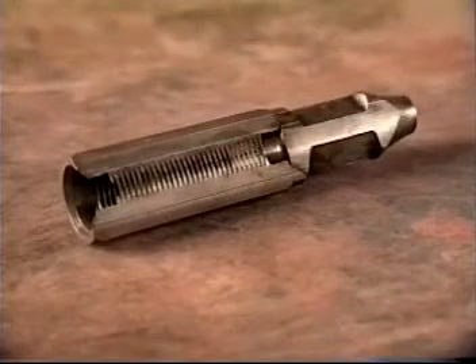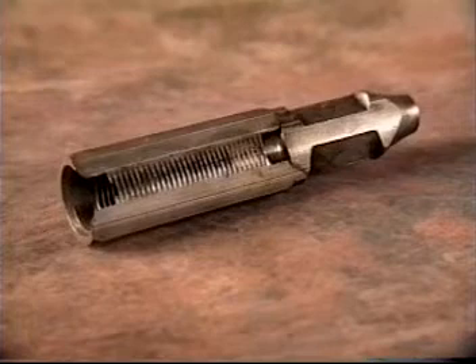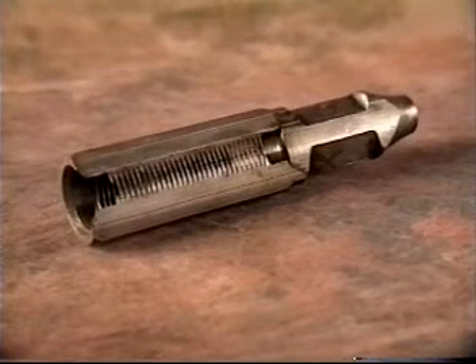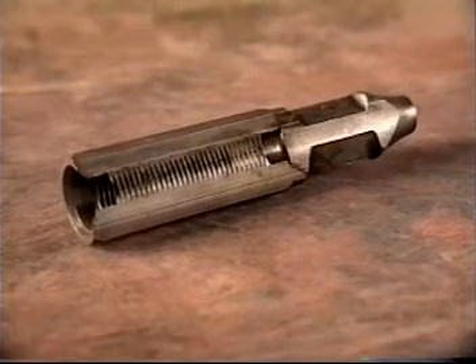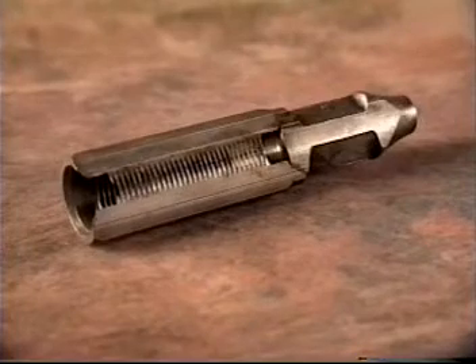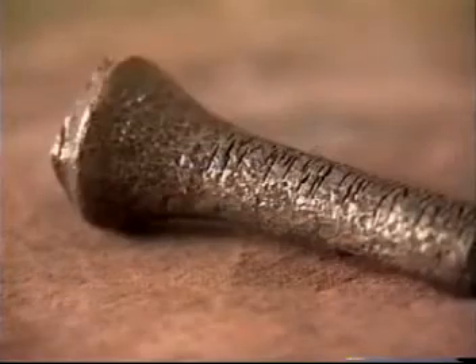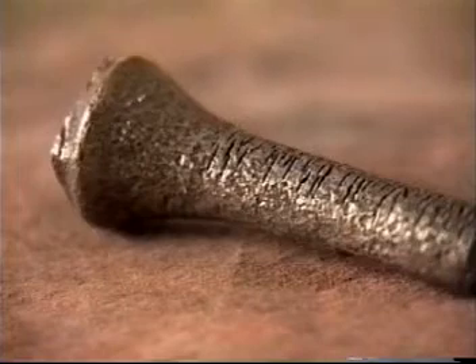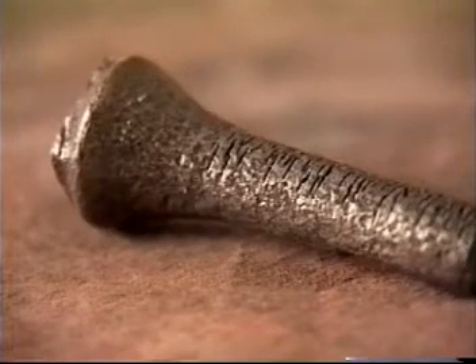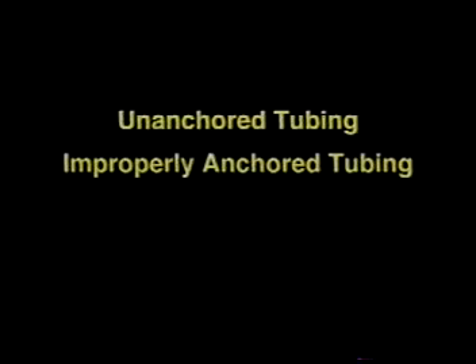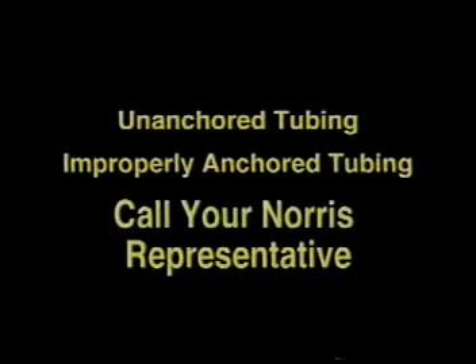Compressive loads will usually result in distinctive wear patterns on the couplings as well as the sucker rods. Look for longitudinal wear patterns that completely erode the walls of the couplings and the rods. Compressive loads also cause transverse stress cracking due to flexing when the rod buckles on the downstroke. Unanchored or improperly anchored tubing can also induce severe wear on steel sucker rods and couplings. Diagnosing rod or coupling breaks that may be attributable to unanchored or improperly anchored tubing is difficult and should usually be referred to your Norris representative.